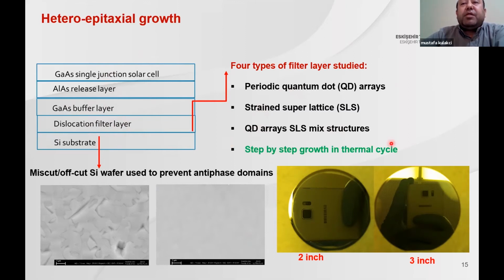But at the end, we end up with the high quality we reach by step growth in thermal cycle, which means some of the dislocation filter layers are produced at different growth temperatures, then go to the thermal cycle at high level, then go back to another growth step, and so on.